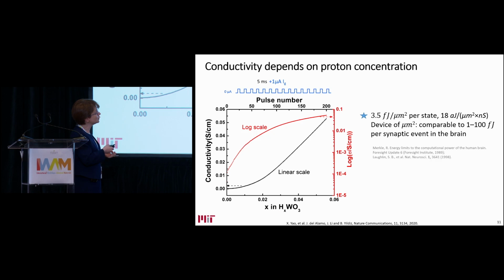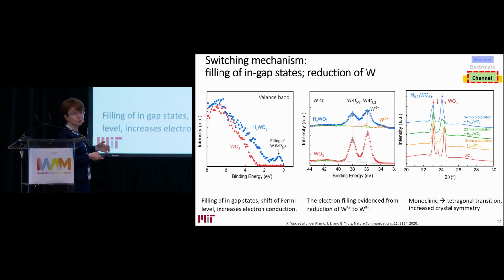And in this first work, we have found that you can indeed get to very low energies per micrometer of device, about 3-4 femtojoule per state. But we were working with rather coarse voltages or pulse parameters. And if you can fine-tune the conductance down to nanosiemens, which is also the target for the field, we projected that one should be able to get on the order of 10, 20 attojoules per programmed state for a micrometer device. We couldn't show that with Nafion because we couldn't really downscale it. And we had to move into those inorganic conductors, as I will show you in a minute.